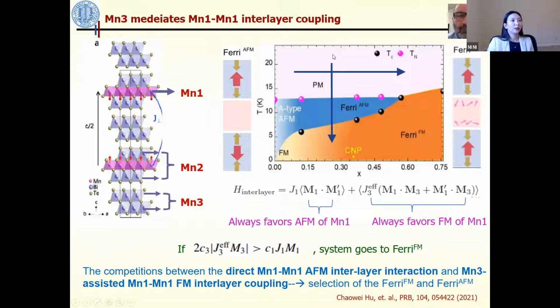Because of this competition, once you have more and more antimony doping, the second term becomes stronger and the ferromagnetic coupling wins. And then if you cool your temperature, your manganese 3, which is paramagnetic, will follow a Curie law. So once you cool down the temperature, again, your manganese 3 magnitude goes up, and therefore, again, your ferromagnetic coupling wins. So this Hamiltonian can help us understand this phase diagram. And mainly it's just because of the competition between the direct manganese 1 antiferromagnetic super exchange interaction and the manganese 3 assisted manganese 1 ferromagnetic interlayer coupling.